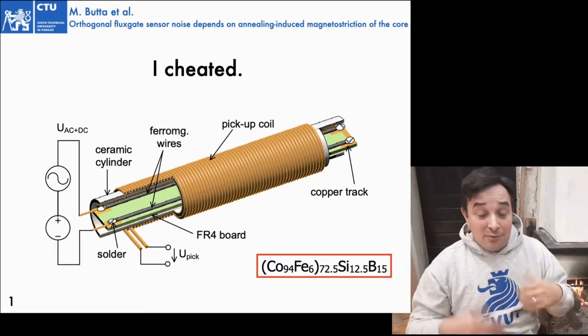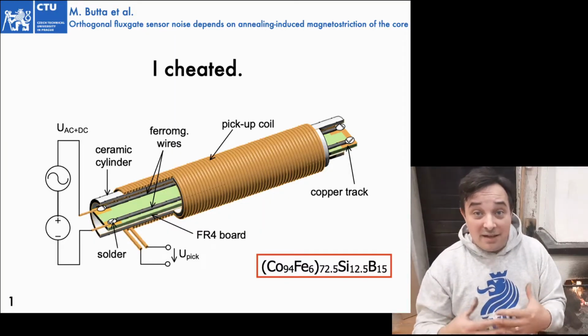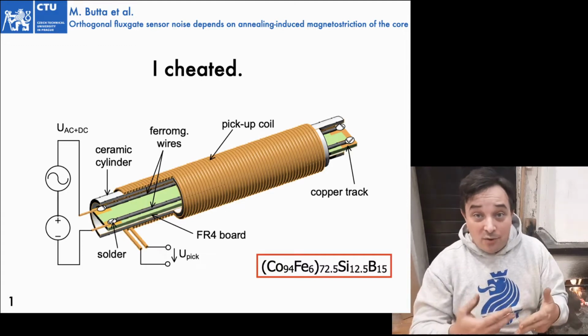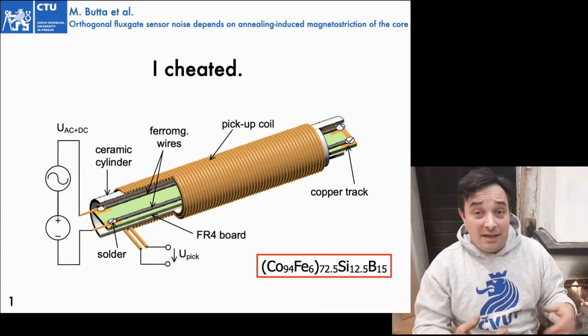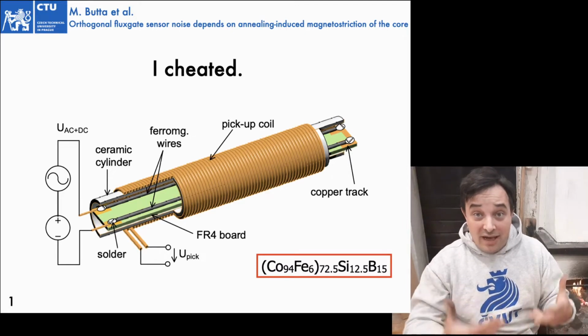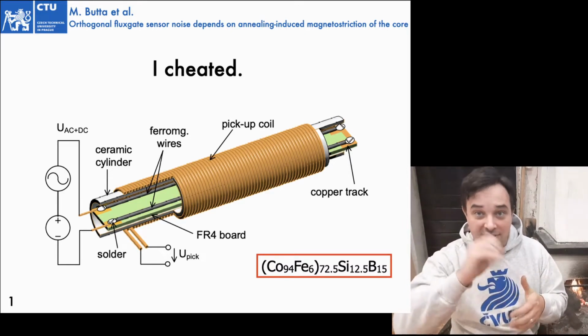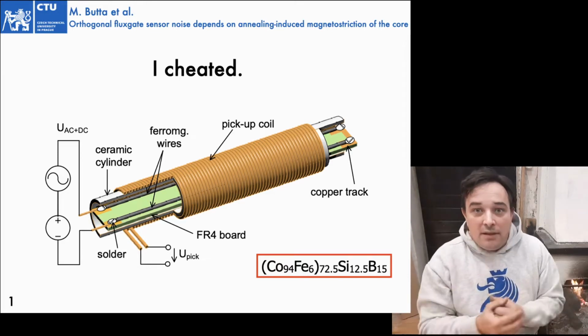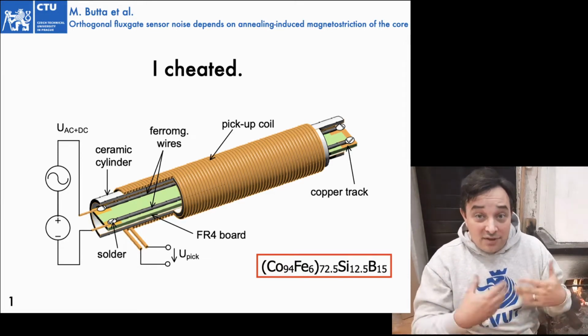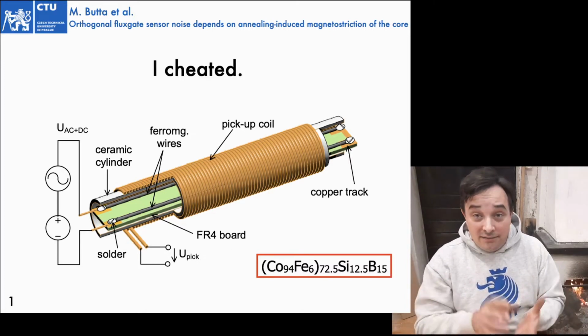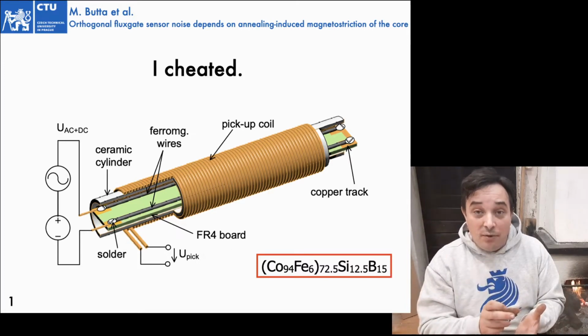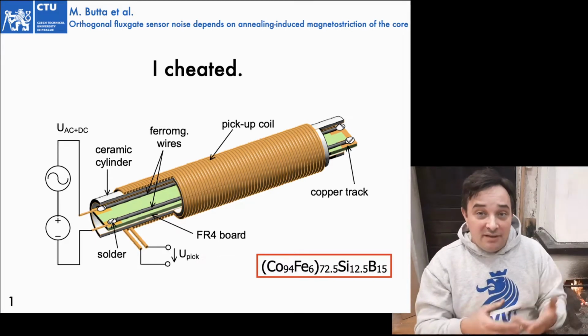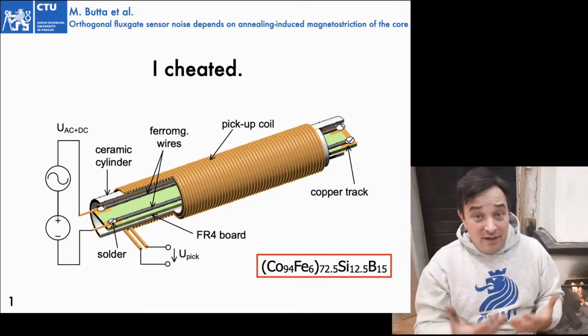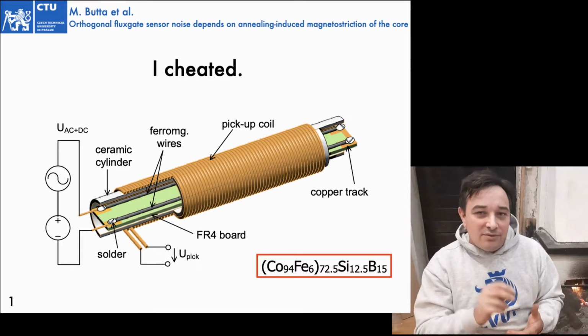A few years ago, I presented a method to reduce the noise in an orthogonal fluxgate in fundamental mode. Just a recap. An orthogonal fluxgate in fundamental mode is a very simple magnetic sensor. You have one or more amorphous wires, which are fed by a DC plus AC current, large enough to saturate the wire in circumferential direction, and you have a pickup coil. If this current is large enough to saturate the wire, then the first harmonic of the voltage in the pickup coil will be proportional to the magnetic field in the axial direction. This is a sensor which has very low noise, but I found a method to reduce it.